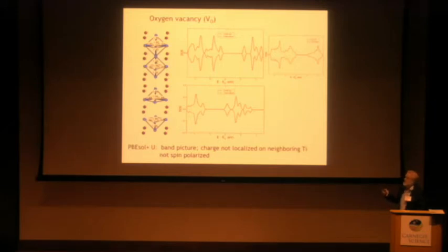And here is, for reference, a more appropriately done calculation with tetrahedral interpolation. In either case, the DFT band gap is 2 eV. It underestimates the experimental band gap, which is about 3.2. The indirect gap is well known.